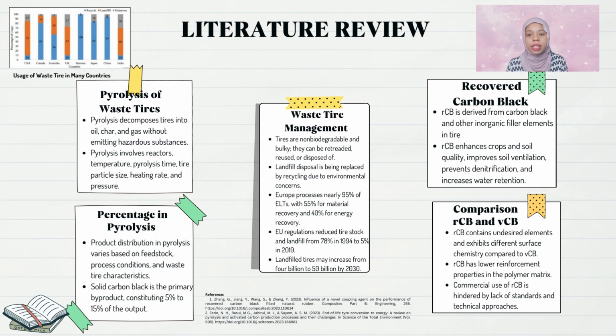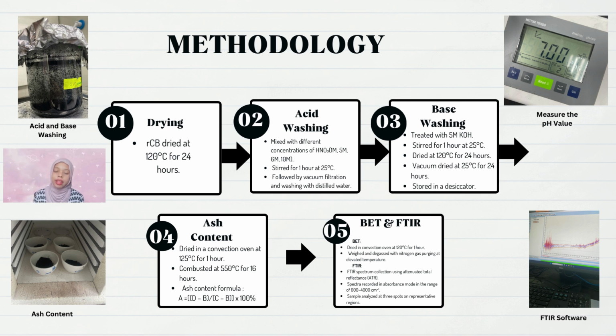reducing reliance on VCB. Our methodology involves several key steps. First, the RCB is dried at 120 degrees Celsius for 24 hours to remove moisture. Then, it undergoes treatment with various concentrations of nitric acid, which is HNO3, and potassium hydroxide, which is KOH. The treated RCB is subsequently washed with distilled water to remove residual chemicals, dried again, and analyzed for ash content, surface area, and functional groups. Techniques such as Brunauer-Emmett-Teller (BET) analysis and Fourier transform infrared spectroscopy, which is FTIR, are used to assess the properties of the treated and untreated RCB.